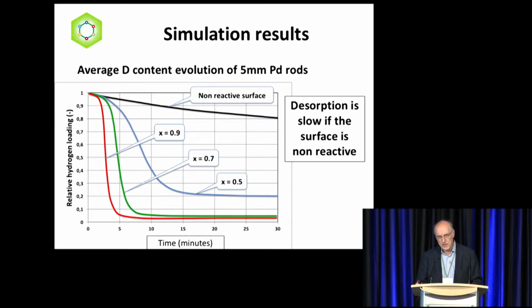The model can also calculate, it's easy for a computer, the average deuterium content in these, for example, here 5 mm diameter rods. And you see that for high loading ratio, 0.9, the outgassing is quite fast. After 5 minutes, you have almost no deuterium left in this piece of palladium. If you have only 0.5, it cools down before all the deuterium is gone, and you are left with some deuterium in it.